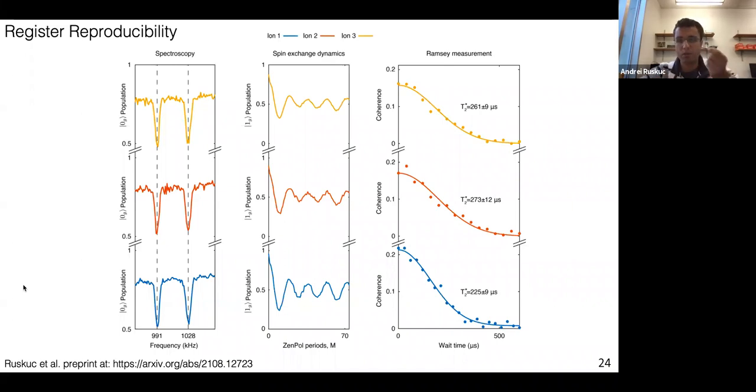But what enables us to address a single atom is the fact that, based on the local environment, the strain environment in the crystal, each of these ytterbium atoms will have a slightly different frequency. And this is your inhomogeneous distribution. Primarily this inhomogeneity we leverage in the optical domain, so we can optically spectrally address different atoms and only work with a single one.